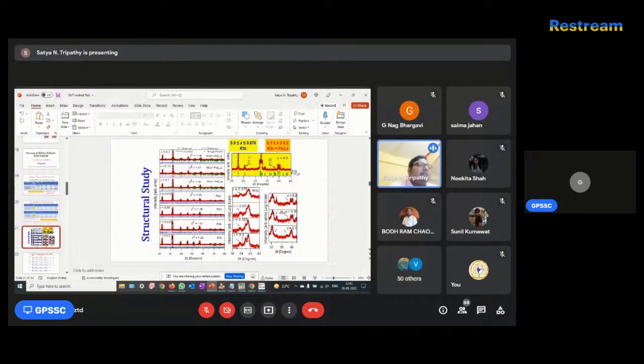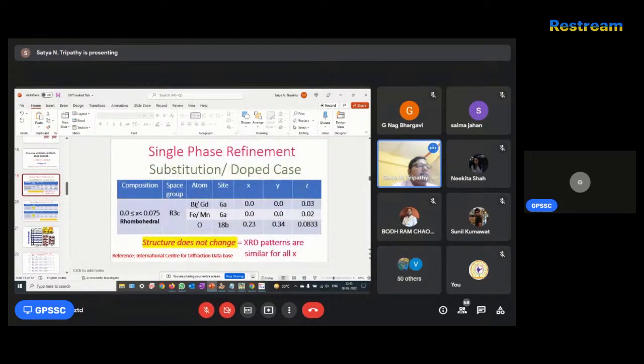Okay, so what is happening? You can see that I have given, on the right hand side, one picture from 36 to 42 degrees. You can see that one characteristic reflection of the R3C phase is there up to 0.075. So we confirm that up to that point, since the XRD pattern is not changing much with gadolinium manganite, we are keeping the R3C structure for refinement. When you do that, you place gadolinium at the bismuth site using the same atomic position, and in case of iron, you use the same atomic position for manganese. There will be 5 elements.